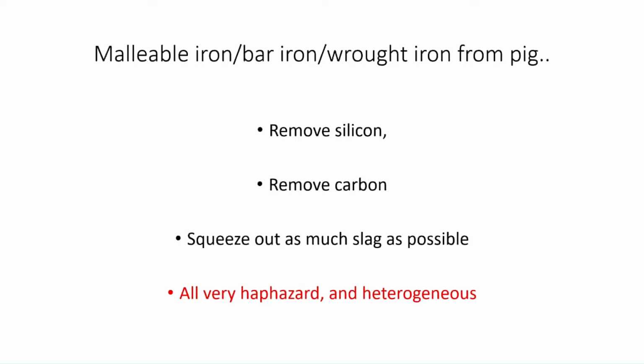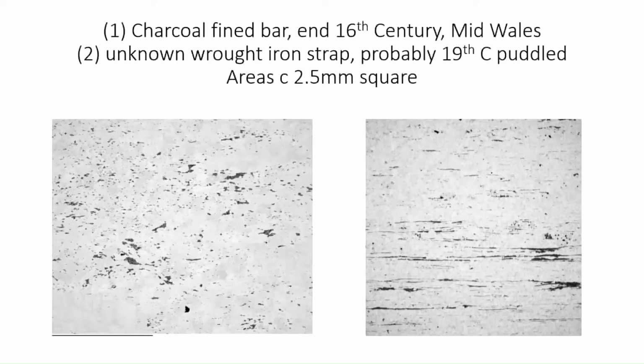So the next thing you do is try and squeeze the slag out. And so you hammer it, you basically treat it as a sponge. You heat it up to well above red heat and beat the slag out of it. The result is this.